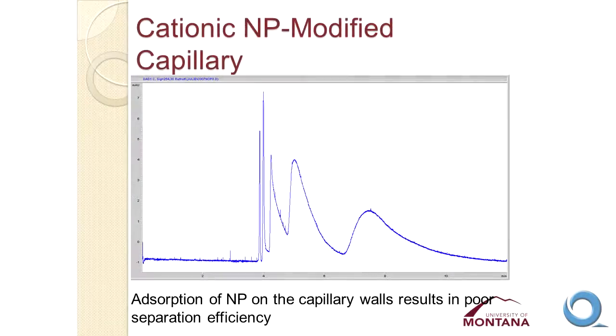So Julie McGettrick, the other student who was on the title slide, has worked this out now. What she has done is to synthesize just the cationic polymer. She's done it by the controlled polymerization mechanism. So she has this nice uniform cationic polymer, and she can use that to modify the capillary walls. She first treats the capillary with this cationic polymer. That reverses the charge on the walls of the capillary. And then when she introduces the nanoparticles, they don't adsorb to the walls because they're repelled by that cationic charge. And then she can achieve very nice high efficiency separations.